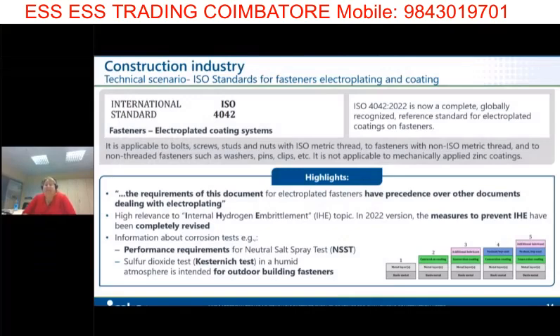And here I would like to introduce to you the ISO 4042, which is a specification for electroplating coating systems. So for fasteners which have on top of the base material some zinc or zinc alloy layer, and then also being passivated and maybe have also additionally a sealer or a lubricant on top. This specification was completely revised last year, and they are now telling inside the specification that the requirements which are mentioned in the document have precedence over all other documents dealing with electroplating fasteners.